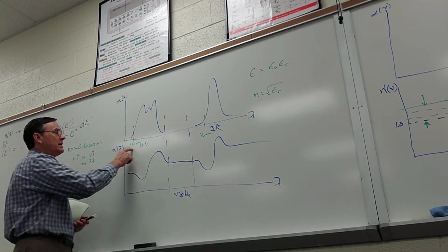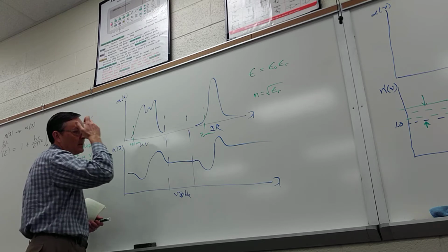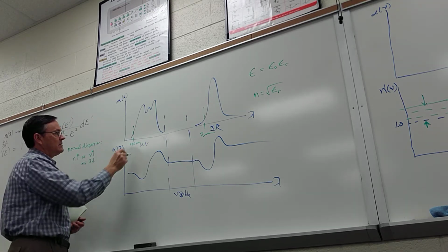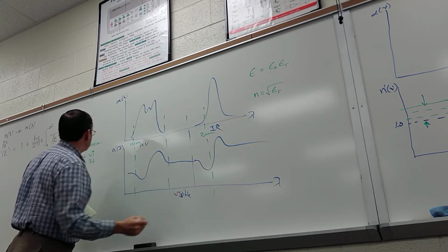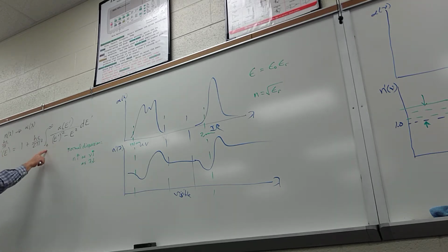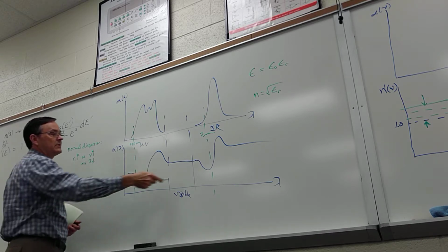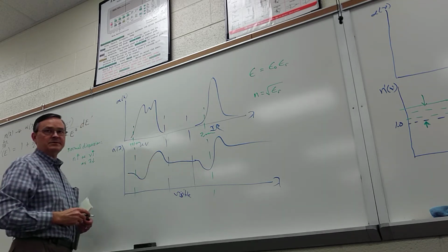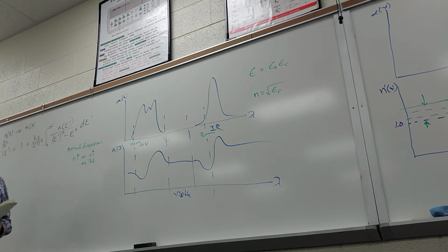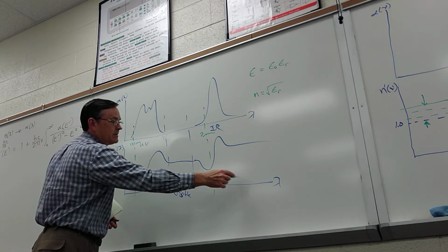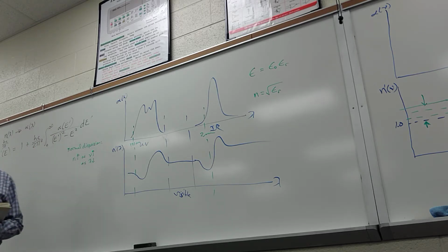So if you can make this measurement of absorption, great, then you can do this integral from 190 nanometers to 2 microns. And in here, you can probably do pretty good in terms of the refractive index. But out here or out here, nah. You're not going to be able to use this to get it. In other words, extrapolating doesn't really work well. You need the measurements for the absorption.